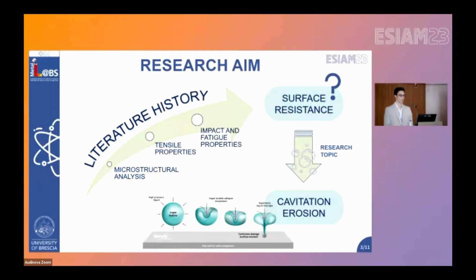Since these components are already used in the mold industry, it is clear that the general properties needed to characterize the stress on the mold are already known. Although less is known about the surface resistance of these materials, and for what regards cavitation erosion, this phenomenon can happen not only in contact with the liquid metal, but even inside the channels of the